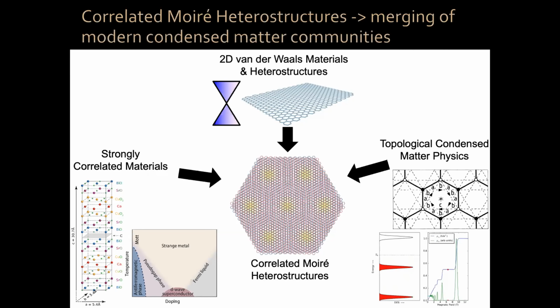And in addition, then we have the possible complexity similar to what happens in the cuprates, that is very different in doping with electrons and holes in the cuprates. Well, it might be that also in terms of correlations here, the behavior is very different when you dope with electrons and holes. So you have these three possible reasons for why the system is not electron-hole symmetric, starting with two which are just at the level of single particle.